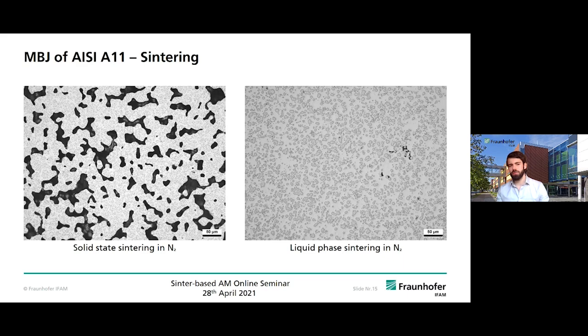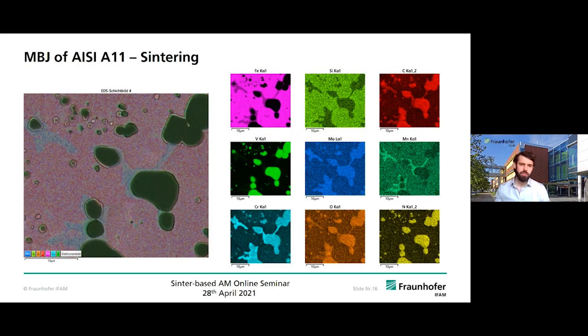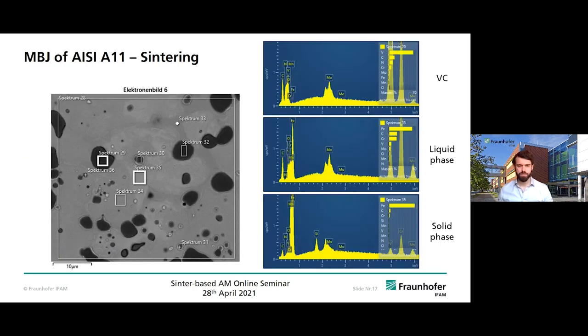for this material. So we switched to liquid phase sintering. So we raised the temperature by about 20 to 30 degrees and reached almost full density with this material. But as we went to the liquid phase, there were also some other reactions. We had some liquid phase, and you may see in the liquid phase there was majorly a higher chromium content as well as manganese. And the nitrogen inserted itself into the vanadium carbides. You can see that more clearly on the next slide, where we have the vanadium carbide, and see that there was an extended introduction of nitrogen inside.